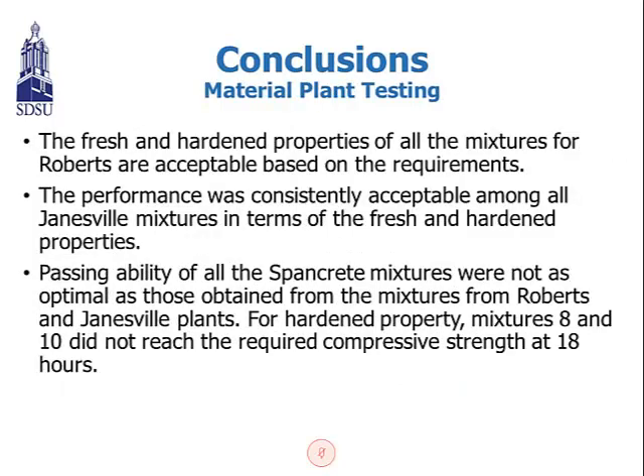And here's a conclusion for the material plant testing. In fresh and hardened properties, all the mixtures were acceptable based on the requirements that we established by discussing the results with the technical panel. And the performance was considered acceptable for all the Janesville mixtures in terms of fresh and hardened properties and passing ability. All the Spancrete mixtures were not as optimal as those obtained from the mixtures from the Janesville plant. For hardened properties, especially mixtures 8 and 10 did not reach the required compressive strength at 18 hours, as I mentioned before, due to the inappropriate curing period.